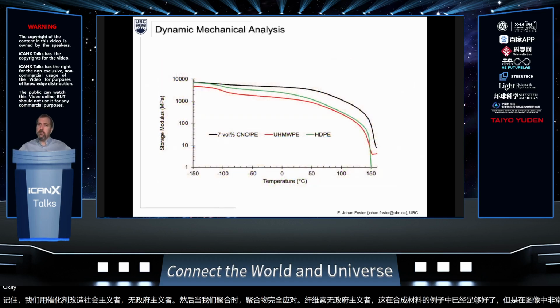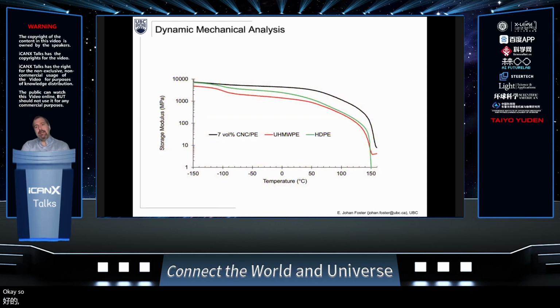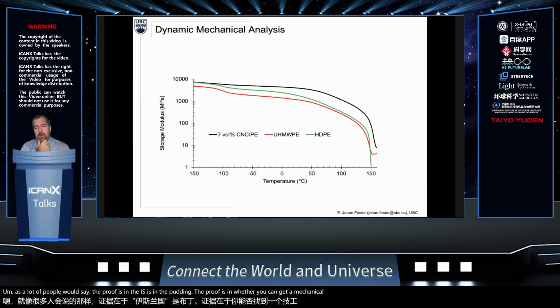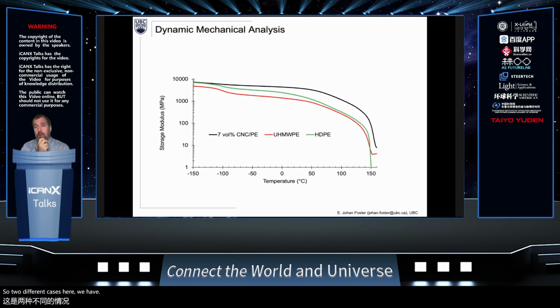Okay. So, as a lot of people would say, the proof is in the pudding. The proof is in whether you can get mechanical reinforcement. So, two different cases here. We have ultra high molecular weight polyethylene, sort of the best polyethylene that's out there, and we have high density polyethylene, which is also a very widely used polyethylene. And we compare that to our cellulose nanocrystal reinforced polyethylene.